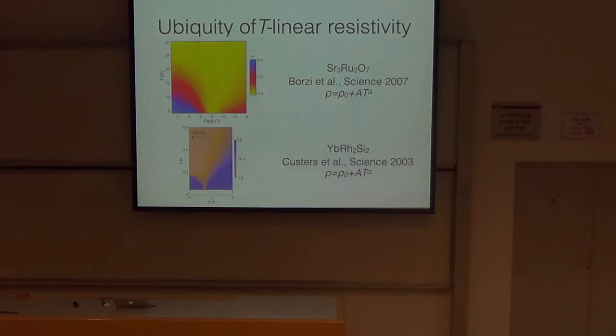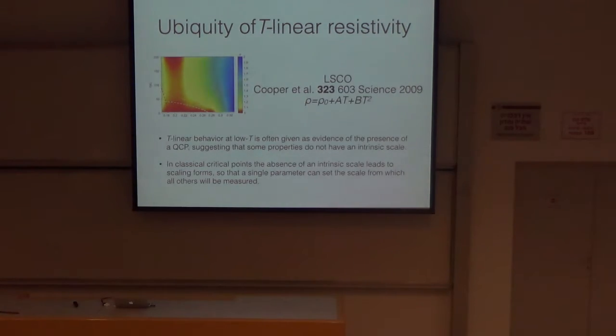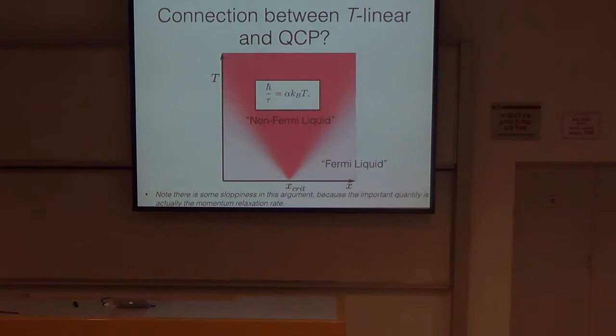Now, this kind of behavior is seen in a number of different systems, not just the iron pnictides: the strontium ruthenate, ytterbium rhodium-2 silicon-2, again with a similar kind of plot here. And also the cuprates are no exception. The basic question is really what's driving this crossover from the T-squared resistivity, which we commonly associate with Fermi liquid-like behavior, to the T-linear resistivity, which seems to happen at some magic non-thermal parameter values. So that might be doping in the case of the cuprates, it might be magnetic field in the case of strontium ruthenate, ytterbium rhodium-2 silicon-2.